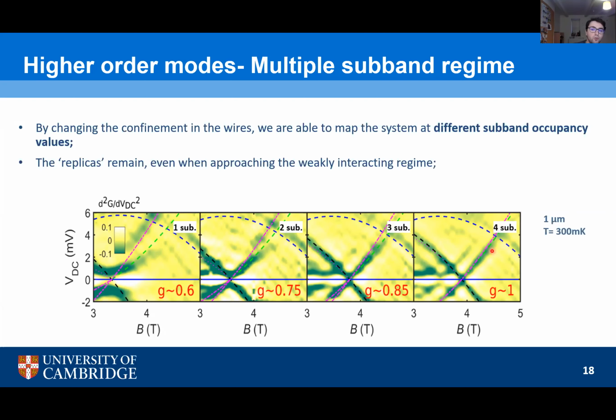And the same thing for 4 subbands, of course, here, they're essentially overlapping. But what we see is that the replicas remain even when we populate more subbands, and it's also responding to the interaction strength. And this is very interesting because all the theory is done assuming only 1 subband is occupied.